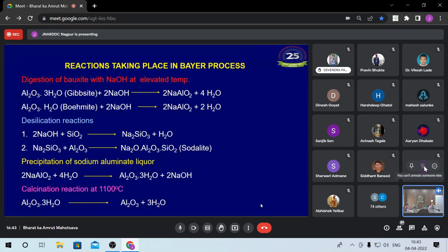The sodium aluminate after filtration is then allowed to precipitate by adding the seed, and this is usually accomplished at a temperature of 70 degrees, and the end temperature of the precipitator is in the range of 60 degrees or even 55 degrees to get alumina trihydrate. And this alumina trihydrate is then calcined at 1100 degrees to get the calcined alumina, which is the starting material for the smelter.